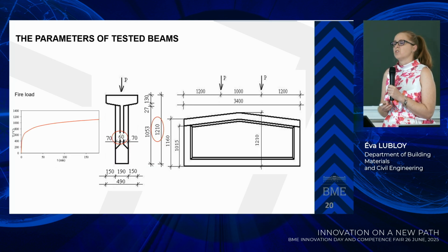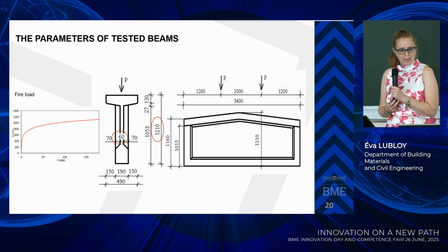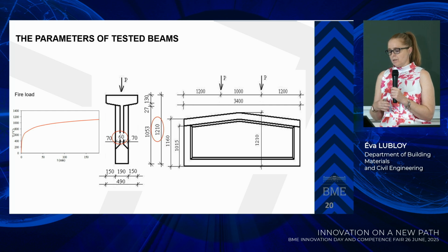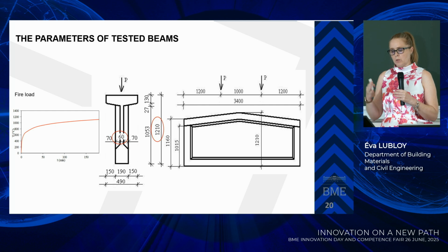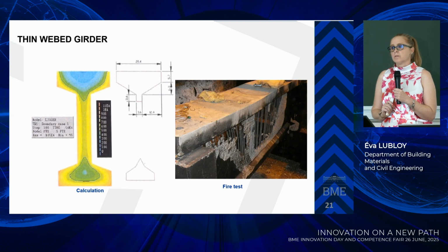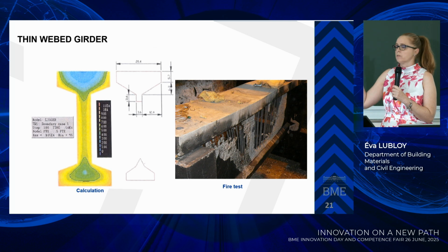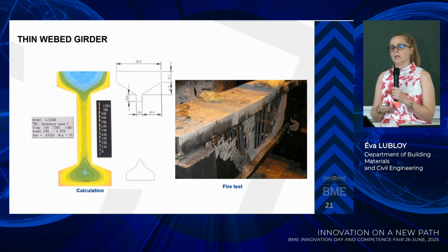The first was about 20 years ago. It was a very interesting element because we have a small girder, 6 centimeters is nothing, and relatively high, above 1 meter. These elements are really dangerous in case of fire because the heating of the girder is rapid. Is it possible to calculate? The answer is no. Because if you use the 500°C isotherm method, then we see that we have no girder. In this case, we have nothing to transfer the shear forces. It is true, so we should make fire tests.